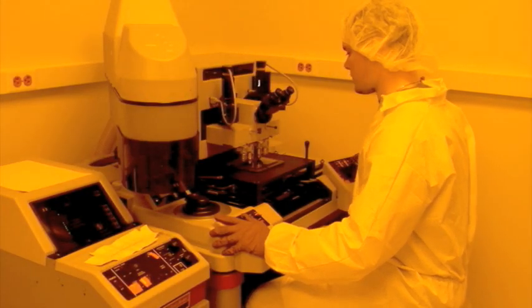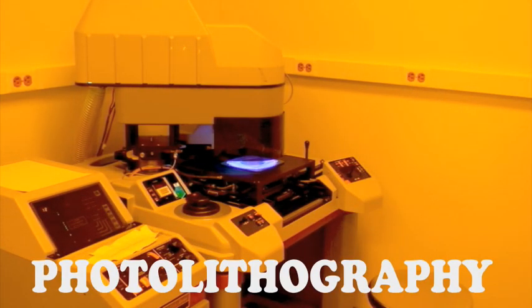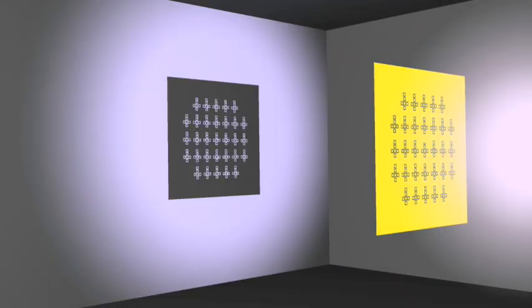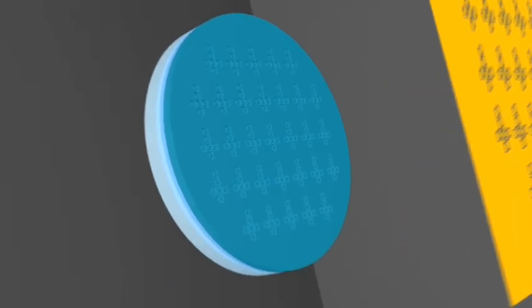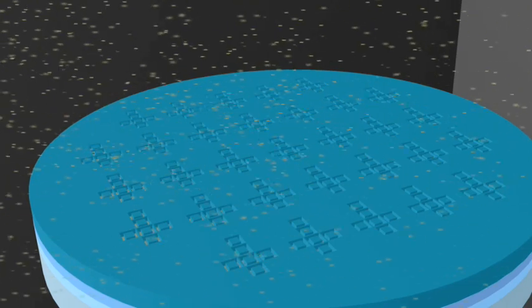In the laboratory, we use a process from the computer chip-making industry called photolithography to make our 2D shapes on a miniature scale. First, a mask is created. It is used to expose a specially prepared silicon wafer, and the areas that are hit by the light dissolve away. This leaves a mold behind which is filled with metal, forming the cube faces.